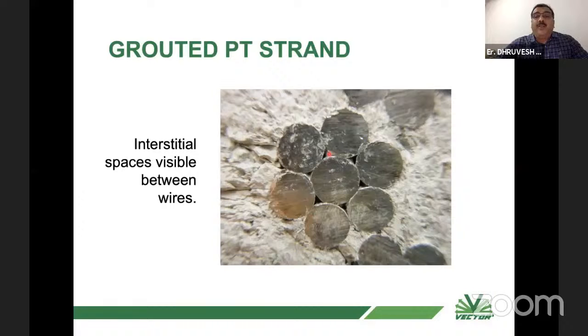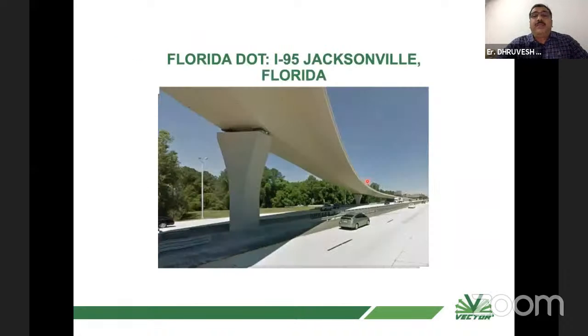You can see the voids in between, which are called the interstitial voids. And these are in microns. So we want to use these voids and these small gaps around the strand. You can imagine a 50 mm or 70 mm tendon having 19 strands and grouted, and this whole 7 wires is hardly 2, 3, 4 millimeter. So the gap could be hardly microns. We want to inject material through this. I will show you this with one of the case studies.